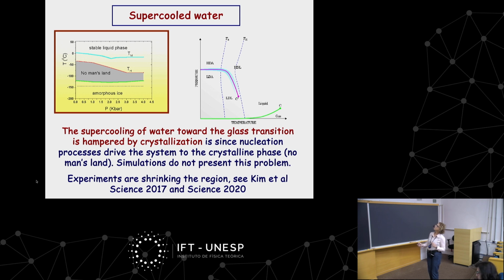What we think is that this first-order phase transition will go into this line to finish in a second-order critical point that, in the two-phase region, separates a high-density liquid from a low-density liquid, and later below, for lower temperature, a high-density amorphous from a low-density amorphous. This is the normal liquid-gas critical point that we all know all substances have, and this is another first-order line of transition, and this is second order, and this one should be second order too.